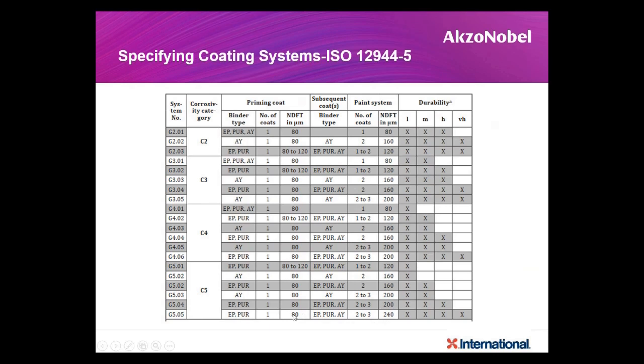240 minus 80 is 160 microns of intermediate coat. Okay. So total number of coats would be 1 plus 3, 4 coats. So if you have a coating system and this is applied on carbon steel after abrasive blasting and proper cleaning, then the durability can be greater than 25 years.